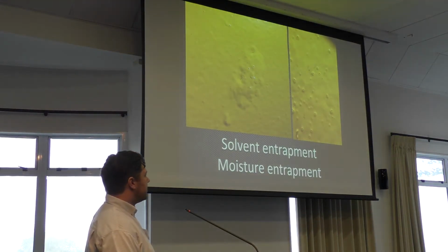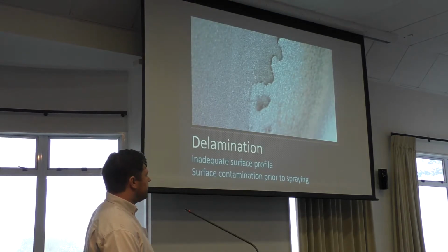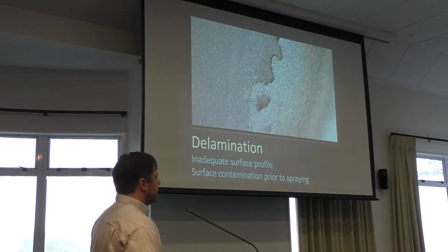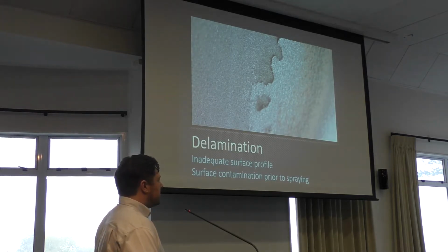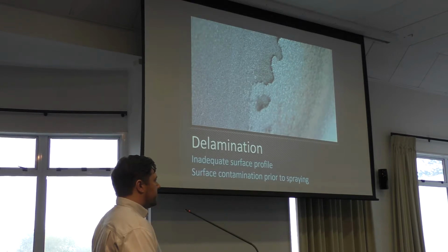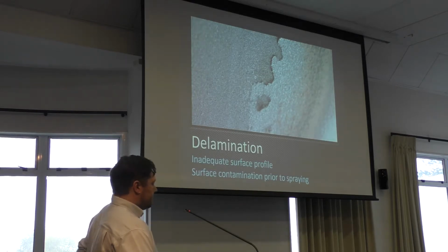Can I make a comment before you go on? Yes. On profile. One of the big things, particularly with welds and cut edges, as you know, is the surface hardening. Yes. And so often the profile that you might get elsewhere on the steel member is not the same over those hardened areas, and that's often where we see this delamination problem. So very important to grind that hardened steel off or use a harder abrasive. Yeah, thanks, Billy. And that's particularly noticeable on the plasma cut surfaces. They get a really hard edge on them.